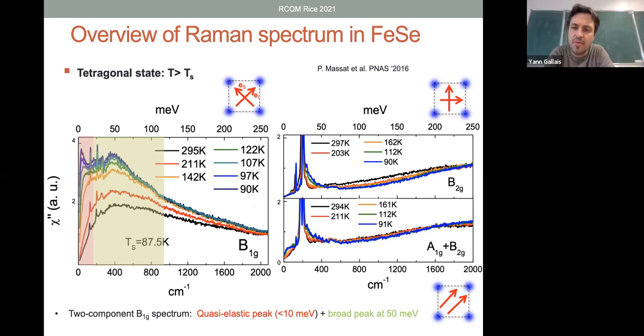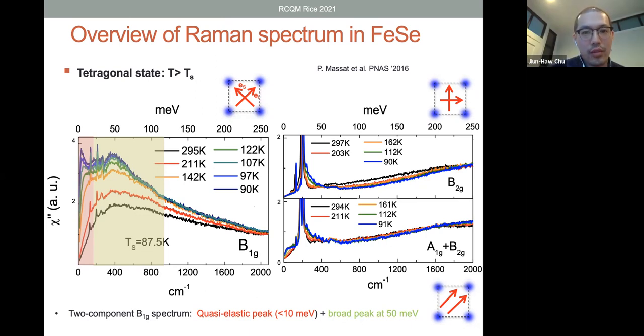But if I remember well, there was a rotation between B1 and B2, right? So in your elastoresistivity data, there is no change of symmetry of these fluctuations? No. That happens very close to the iron telluride side. So in the 50-50, it's still dominated by B1g in your definition.